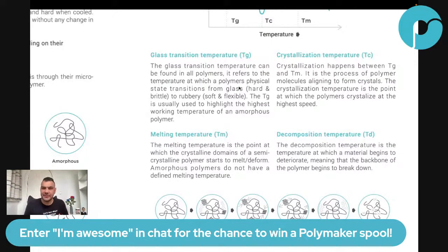Okay, so that's TG. TC, and sorry for the guys that were here on Saturday, because I explained this on Saturday. So TC, the crystallization temperature, the temperature at which the polymer has the highest kinetic energy to create crystals. That was not the best way to say it, but crystallization happens at almost any temperature. The TC is the temperature at which it happens the fastest. Does that make sense? If you're above TC, it will happen and de-happen at the same time, so the rate at which it builds is very slow. Below TC, the polymers are too slow, so they crystallize very slowly. At TC is the perfect temperature. They come together very quickly and not too fast that they break again.